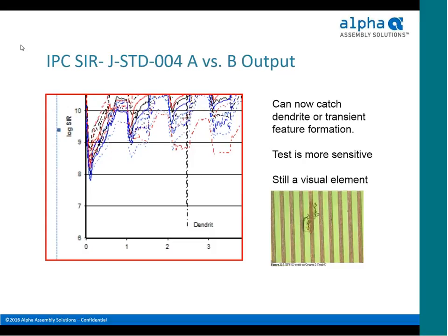So in this case here, very unlikely that the J standard 004A test would have seen it through the automated test measurement systems. It would have still been seen with the visual inspection. However, I think everyone here would agree that visual inspection is not quite as robust as collecting automated data. So an improvement here is that the test resolution is much finer and can detect very small transients that weren't detected under the old static methods.